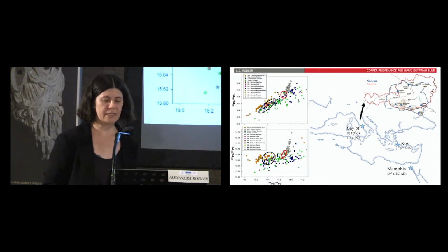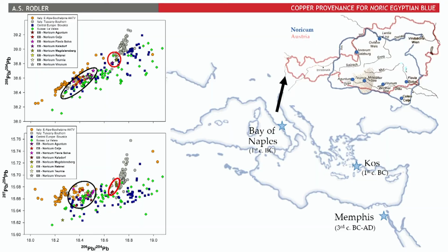So here are the lead isotope biplots for samples from Noricum. So the Noric Egyptian blue samples are plotted as stars again. They show good overlap with the copper ore deposits from Eastern Alps, Switzerland, and also Slovakia, so with Central European copper ore deposits. And also there seems to be two subgroups, with the bulk in the left ellipse and the smallest subset here in the smaller circle. So this second smallest subset still matches Central European copper ores, here also from Switzerland, for example, and from Italy, but there could have been a slight change in supply of materials between the 1st and the 2nd century AD.